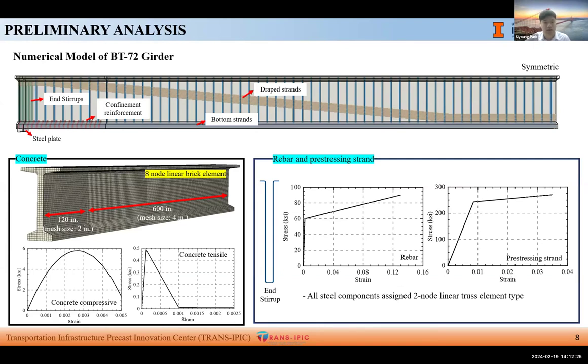Compressive and tensile stress strain curve was designed as shown in the graph, following the Hognestad parabola and ACI code. Compressive strength of the concrete was set as 5.8 KSI based on PCI bridge design manual, and tensile strength was calculated following the ACI code. All steel components were specified as T3D2, which is 2-node linear truss element type, and yield strength of rebar was defined as 50 KSI, and pre-stressed strands were designed to be 7-strand wire strands with ultimate strength of 270 KSI.